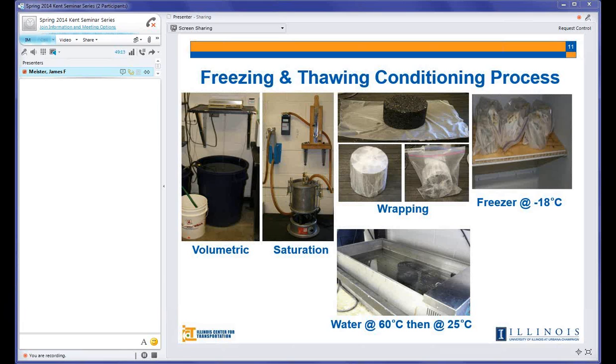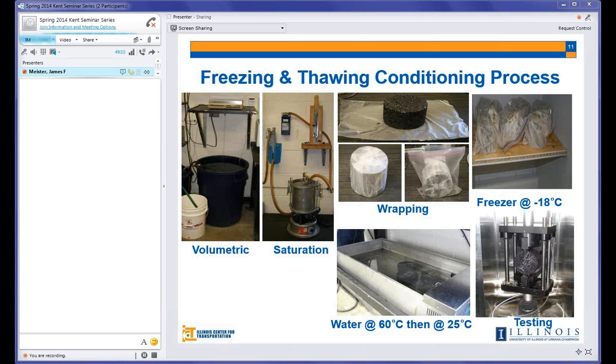For the last thawing cycle, we take the sample from the 60 degrees water bath, put it for 2 hours in a 25 degrees water bath, and then the samples are ready for testing. This is an IDT sample. The same thing was done for the push-pull sample, but of course the sample dimensions are different.